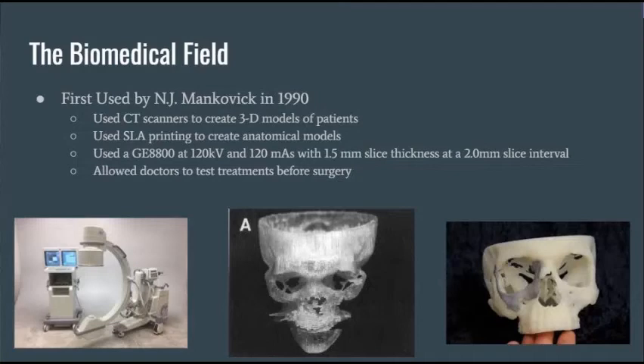The biomedical field integrates CT scans and additive manufacturing technology in one of the biggest ways. It was first used by N.J. Mankovic in 1990. He used CT scanners to create 3D models of patients' internal bone structures. Then he used SLA printing to create anatomical models that exactly match that human structure. He used a GE 8800 at 120 kilovolts and 120 milliamp seconds with 1.5 millimeter slice thickness at a 2.0 millimeter slice interval. This allowed doctors to test treatments before surgery.